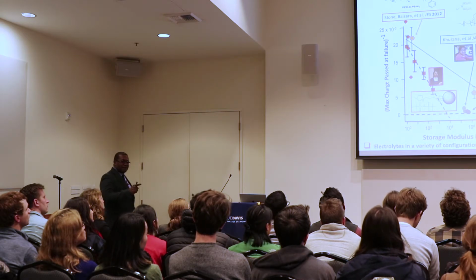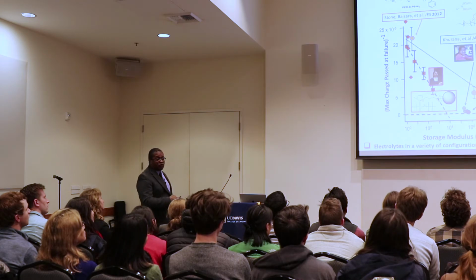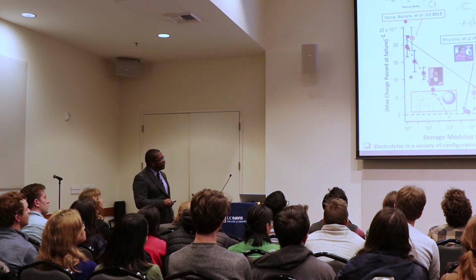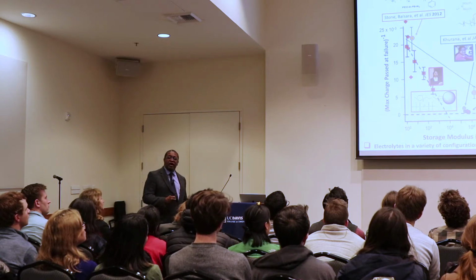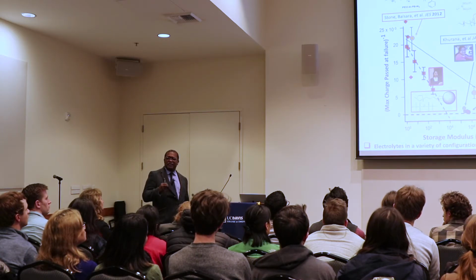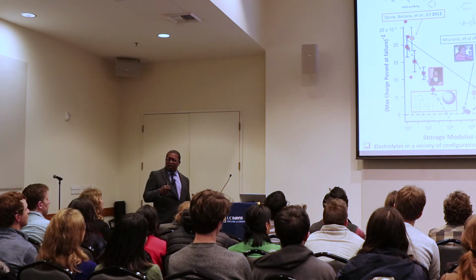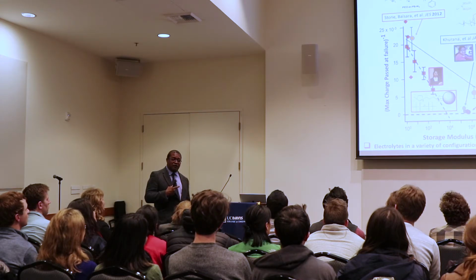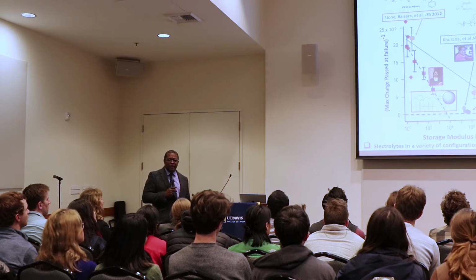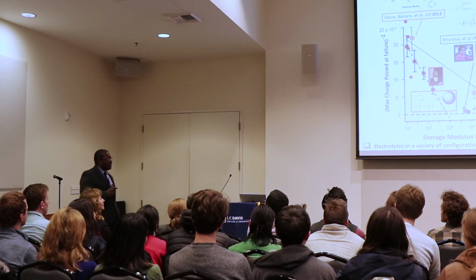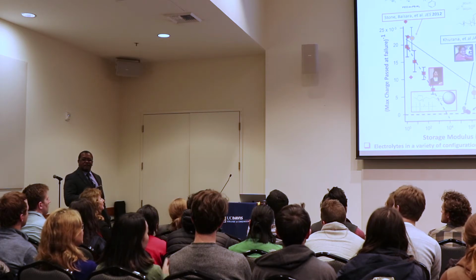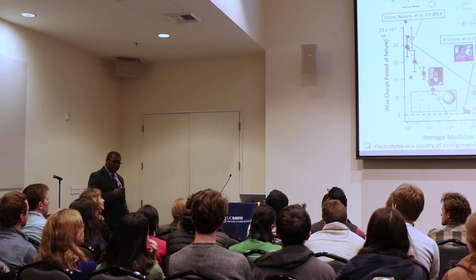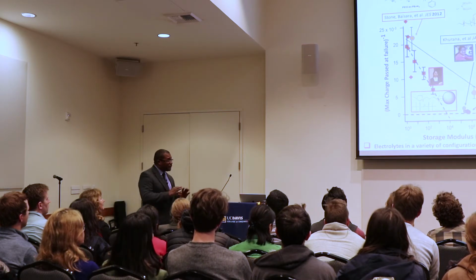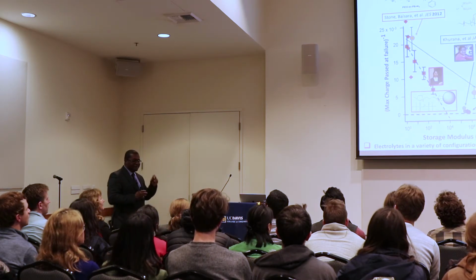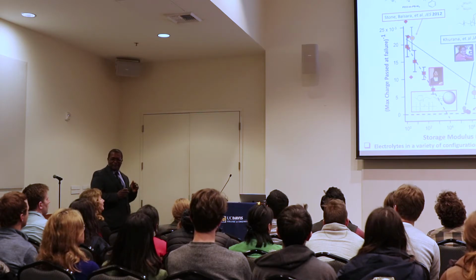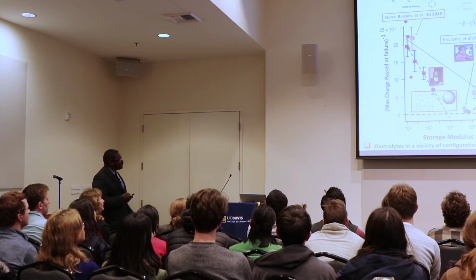In fact, the only exception is older results done by the group that invented this method, using block copolymers, where the intersection occurs almost exactly at the modulus of the metallic lithium, indicating that our approach does not work for this particular system. That was a bit of a puzzle, and I think I know why, but I don't usually say it in public, all right? But for whatever reason, this one example—which is I think the most elegant, a block copolymer that just spontaneously forms nanostructured domains—this method does not appear to work. We can come back to that, all right? So that's good.